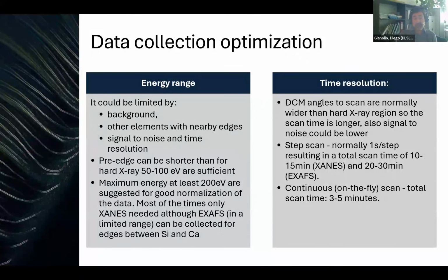It is true that most of the time only the XANES is needed, or a short EXAFS, and a short EXAFS can be collected, as we said, for the edges between silicon and calcium. And in terms of time resolution, we need to consider that when we work with DCM, normally to reach these energies, we are working at very high angles. So this means that if we have a limited speed for the scan of the monochromator, more time is needed to perform physically the scan. And working in a region where air or any other windows could absorb, the signal to noise is expected to be lower.